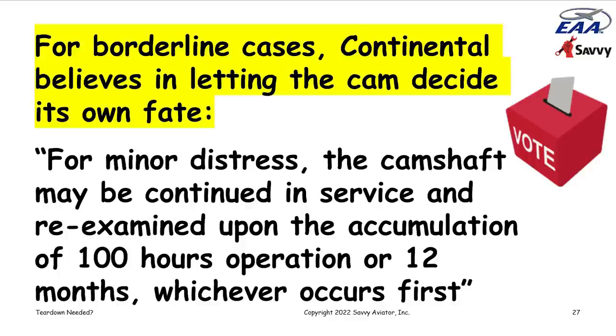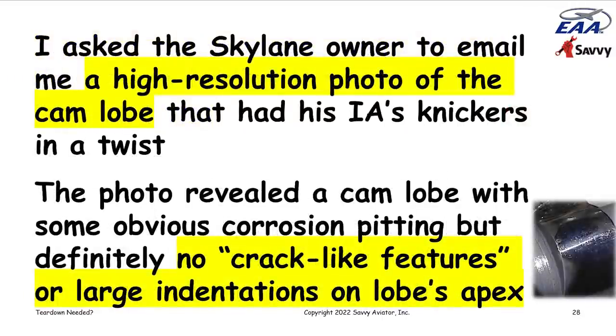And the important thing to understand about these cam and lifter things is that cam and lifter problems are the primary reason that engines get torn down prematurely, before TBO. And cam problems are typically related to intermittent use or disuse, where the cam develops corrosion, pitting, and so on. The point is there's really no risk in leaving the cam in service and allowing it to kind of tell you whether it's okay or not by giving it a chance and taking a look and seeing what it does with the lifters.